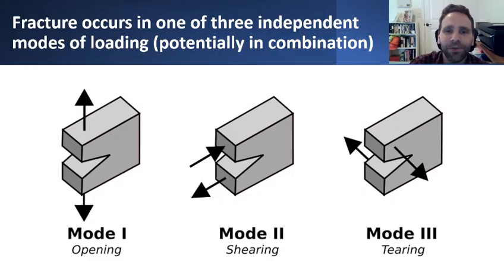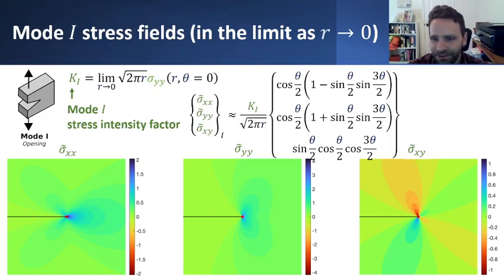So in the mode one case, where the stresses are trying to pull the crack open in this mode one opening mode of fracture, the stress field looks kind of like this. Assuming that you've computed your mode one stress intensity factor from your elasticity solution, wherever it came from, or maybe you've pulled it out of a table somewhere for whatever particular geometry and loading scenario, you can determine what that mode one stress intensity factor is, and then plug it into this resulting expression for the stress field local to the crack tip.